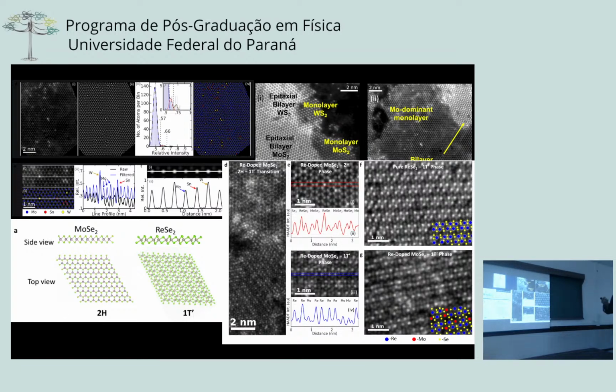Remember, one is metallic, another is semiconductor. So you can make this in-plane heterostructure of metal and semiconductor at atomic scale. What you see here, these atoms, you can see an atomically sharp interface we can make out of two different phases. And all this can be done by changing the precursor concentration, and you can have different phase transformations.